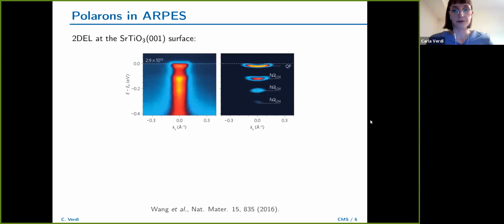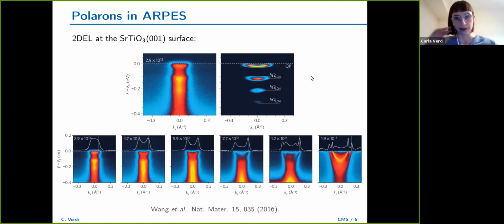And this is another famous example published in Nature Materials, and it's the 2D electron gas at the surface of strontium titanate. You see the band here, followed by a satellite. There is this cascade, but it's kind of due to background signal. And again, the second derivative plot really helps us in discerning the real spectral features. And you see that, again, there are these satellites that are spaced at multiples of the phonon energy. And again, we can observe the evolution of this behavior with doping, and we see that again, at highest doping, we have more like a kink and a very broad tail rather than the satellite features.